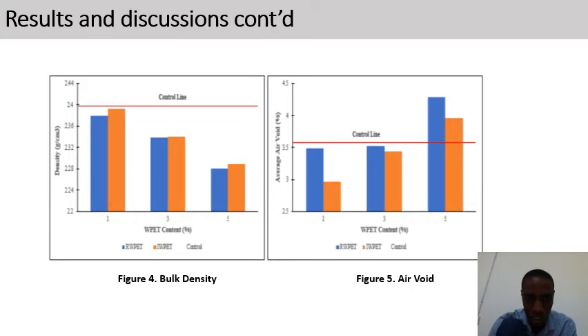The discussion continues with the density, the effect of this PET on the density. As expected, definitely, because the unit weight of this aggregate is less compared to that of the conventional mineral aggregate. Therefore, there is a decrease in density as the waste PET content increases in the mixture.